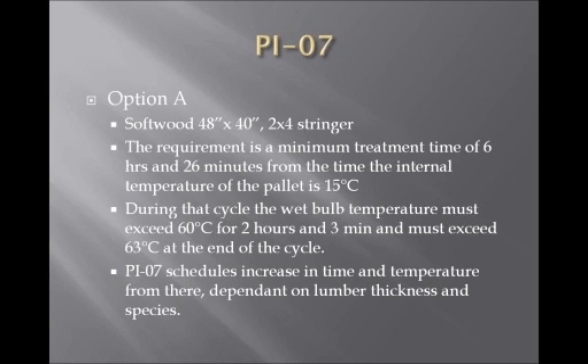Typically, in most chambers that I've seen, your wet bulb is anywhere between 10 to 20 degrees Celsius different from your ambient temperatures, and that depends on location, size of the chamber. The PI-07 schedules increase in time and temperature requirement from there depending on the lumber thickness and species. When we get into mixed runs or hardwood runs, we need to evaluate which category of the PI-07 it falls under. Primarily, items falling under option A are your softwoods, and option E is the most common schedule for hardwoods.